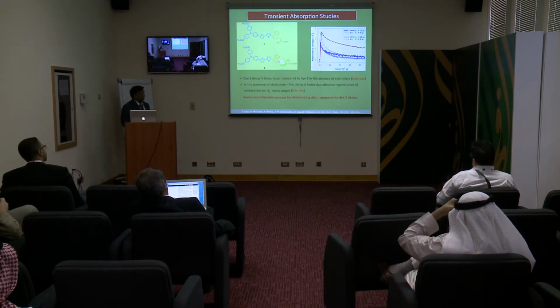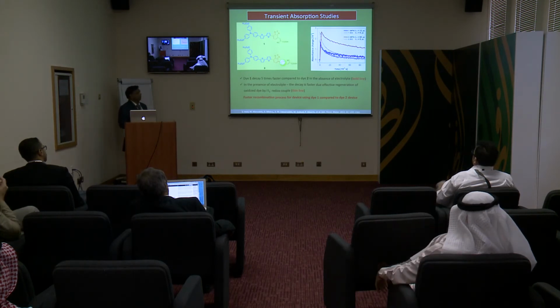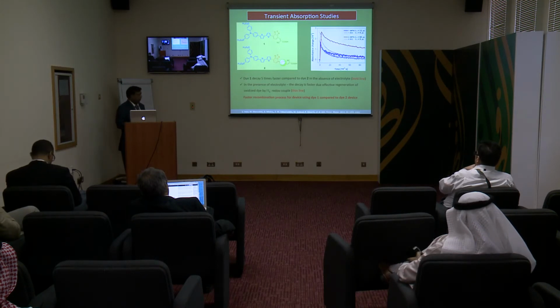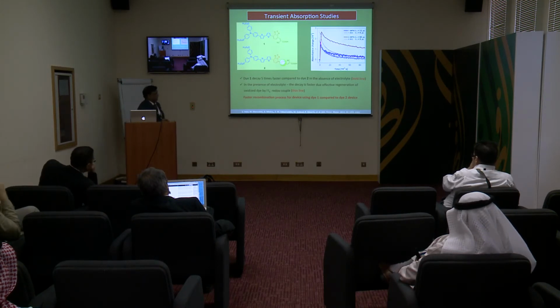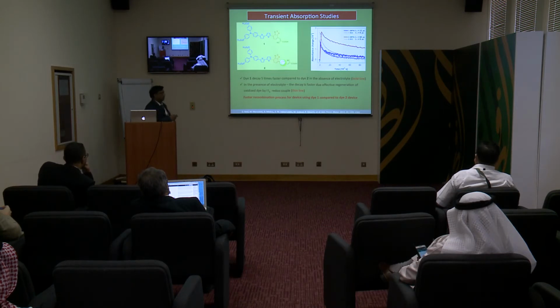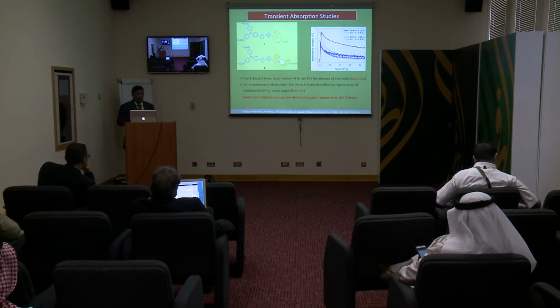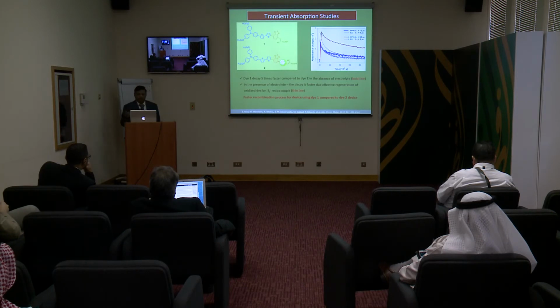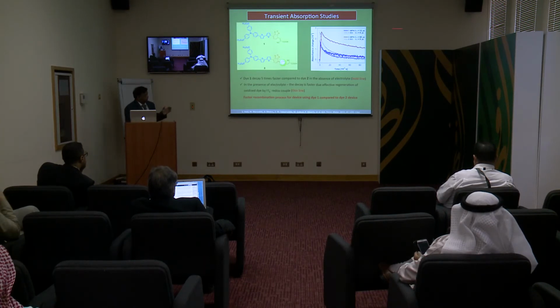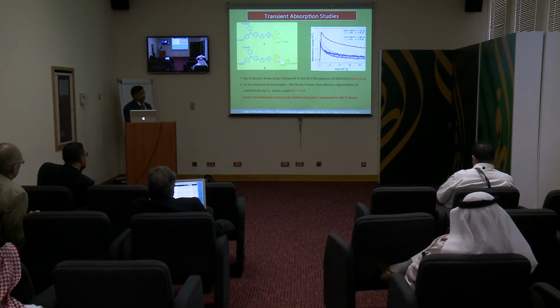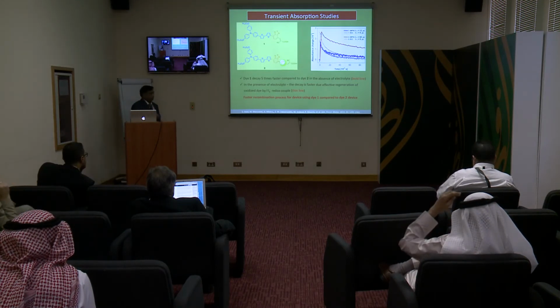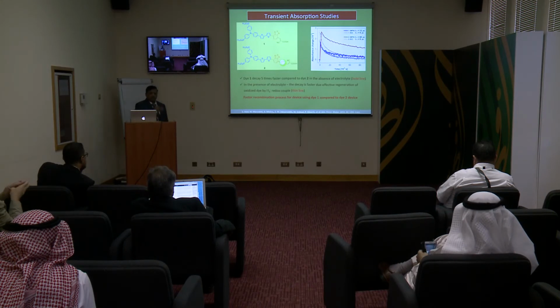So we do this transient experiment with laser photolysis to monitor whether there is a recombination or not. Here we excited the dye adsorbed on the TiO2 to the excited state, it injects an electron, and then you monitor the oxidized form of the dye, how it is decaying. One is in the presence of the electrolyte and one is in the absence of the electrolyte. In the absence of the electrolyte, the injected electron recombines with the oxidized form of the dye, and for dye 2 this takes a long time. Whereas in the case of dye 1, it immediately disappears.